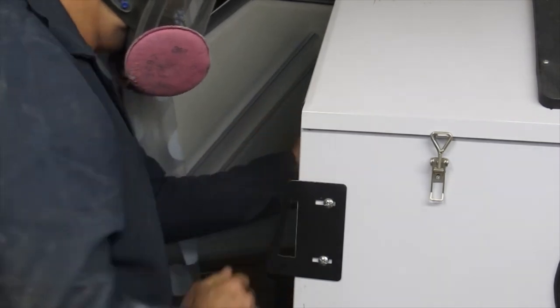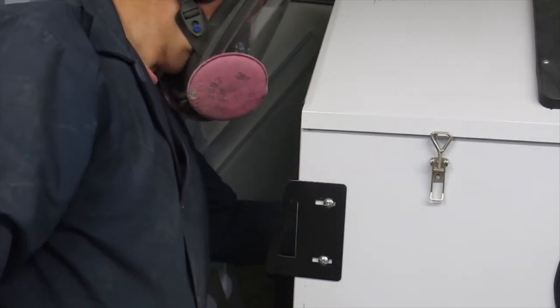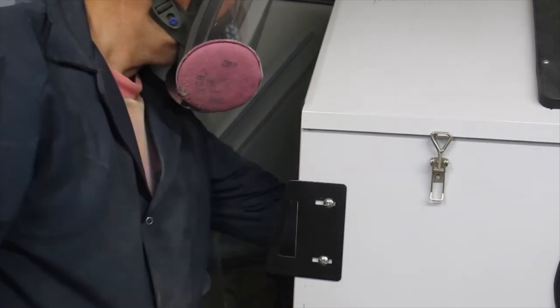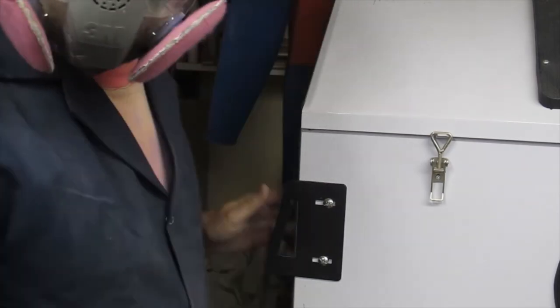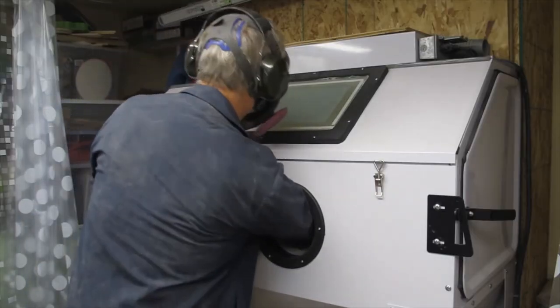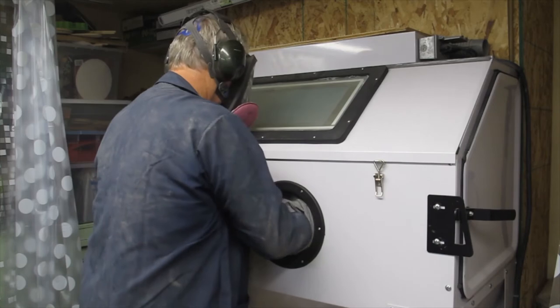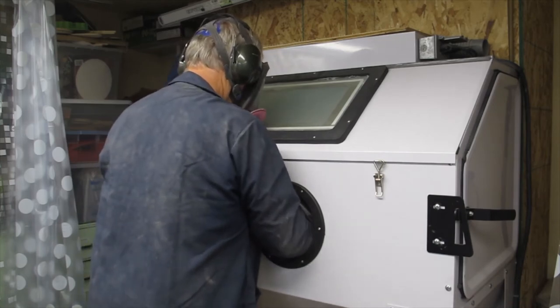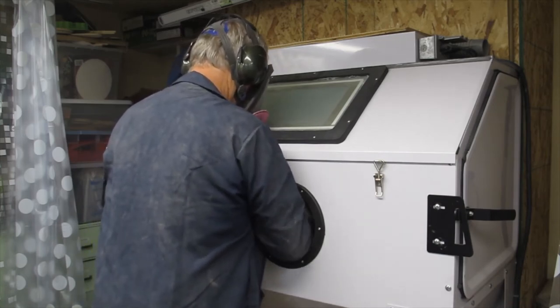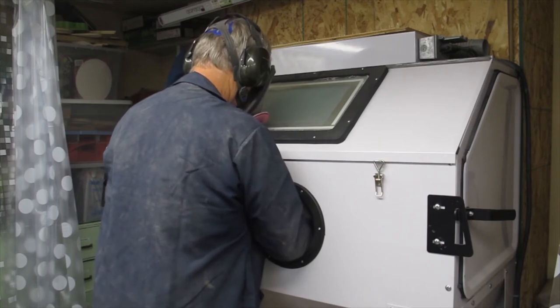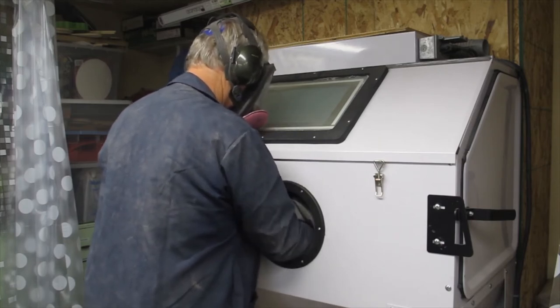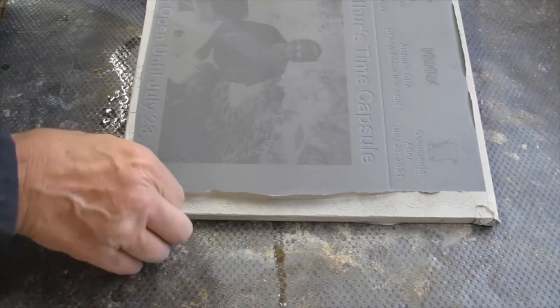Time to put the tile into the sandblast cabinet. This is where 25 years of experience comes into play. Not enough blasting and the image isn't etched into the stone. Too much blasting and the mask will tear and ruin the tile. After completing the sandblasting, I will remove the tape and the mask.